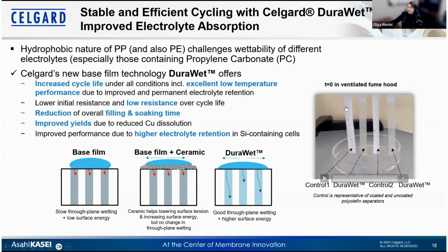So by that, you can see that the control separators are actually repelling the electrolyte pretty fast after a few seconds, while the DuraWet separators really continue to be soaked in electrolyte. And this keeps up for several minutes in a ventilated fume hood until eventually the ventilation will also evaporate the solvent.